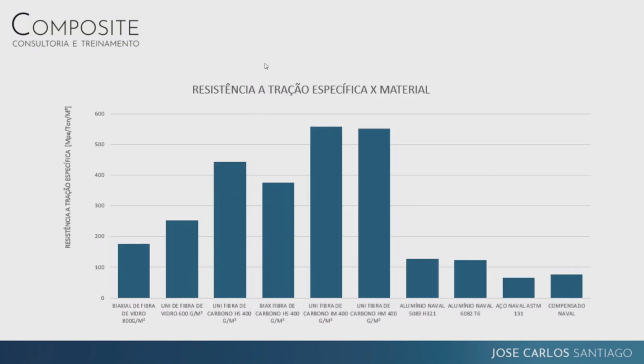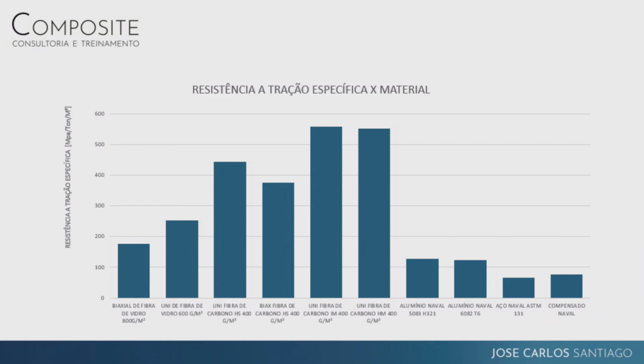The same thing will happen with the tensile strength, the strength on its own, and the specific strength. When we divide carbon fiber, which had a very high strength, by a very low density, 1.6, 1.56, it will have more advantages over the materials. But there is an interesting point. When we divide by the density, even the glass fibers have an advantage compared to the metals, particularly the aluminum. And when we put one chart over the other, it's clearer.